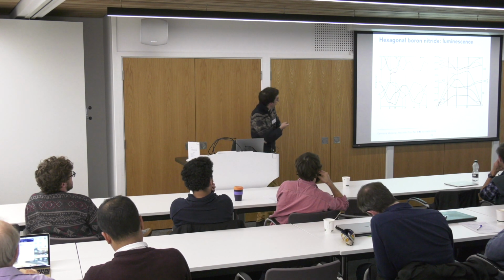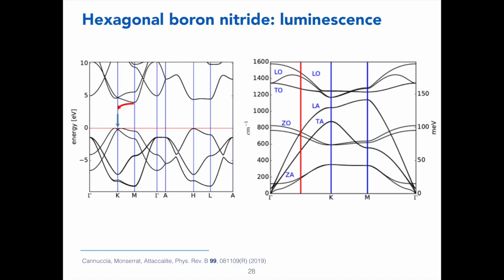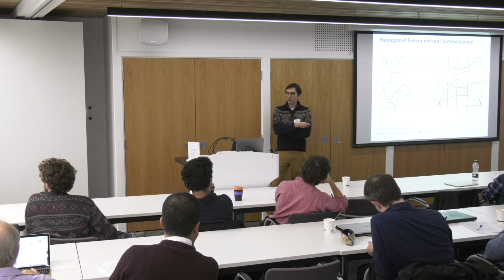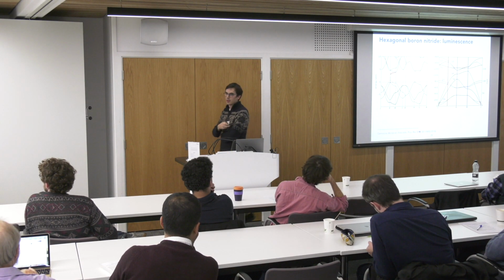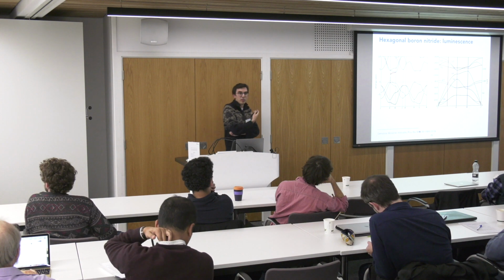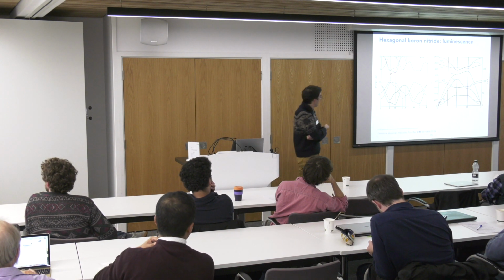So the example here is hexagonal boron nitride. So we're looking at the 3D version of hexagonal boron nitride. At the moment, the 2D version is also very much of interest, but here we're looking at the 3D version, which happens to be an indirect bandgap material. So the bottom of the conduction band is at the M point, and the top of the valence band is close to the K point. And this material actually has a surprisingly large luminescence, despite the fact that it's an indirect bandgap semiconductor. So we're trying to understand how that came about.